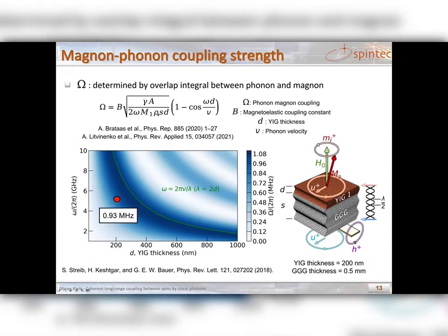So the blue line represents the measurement along the ferromagnetic resonance, and what you see is that a dip appears when the Kittel mode intercepts an acoustic resonance. Away from this magnetic resonance, the line shape distortion is dispersive-like, and it actually represents a Fano resonance. And very far away, it becomes a peak, which mostly captures the acoustic character, but seen through the spin system. And already you can see that this simple analytical model captures most of the features that were observed in the previous experiments. So what about the coupling strength?